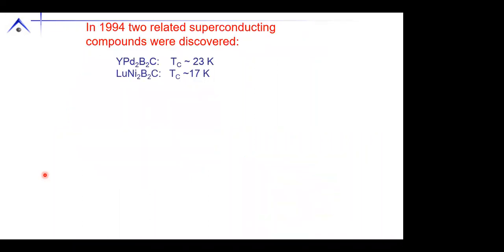So in 1994, there were 2 related families of, at that point, relatively high temperature superconductors: yttrium palladium 2 boron 2 carbon and lutetium nickel 2 boron 2 carbon, with TCs of 23 and 17. The 23 rivaled the highest electron-phonon TC at the time, so it was really quite interesting. It gave a hint there was still some gas left in electron-phonon superconductivity.